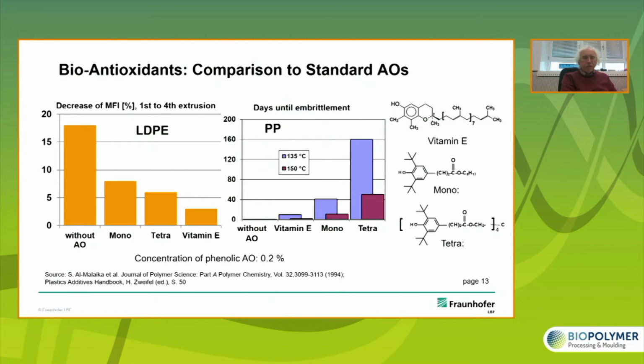First, LDPE and PP in comparison to antioxidants. You see the structure on the right-hand side. First of all, let's look at LDPE. LDPE with aging increases the molecular weight. That means MFI is decreasing. In this slide, you see if I have LDPE and do not add antioxidants in processing, the melt flow will decrease by 17 to 18% after 4 extrusions.